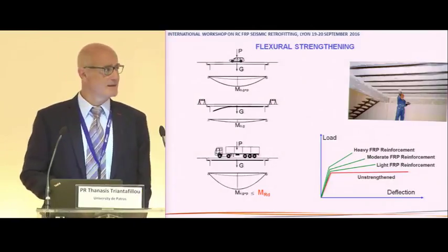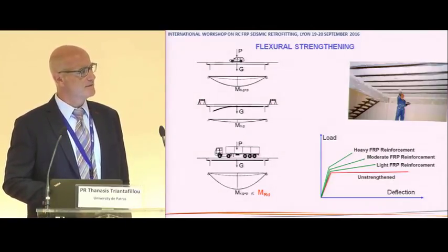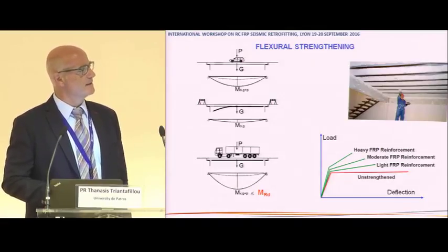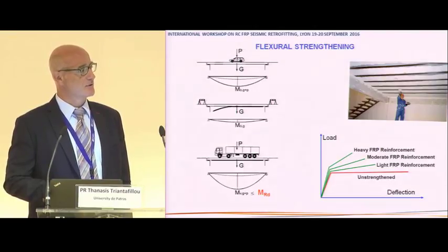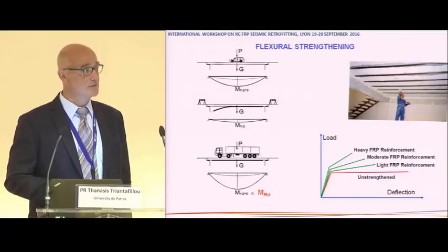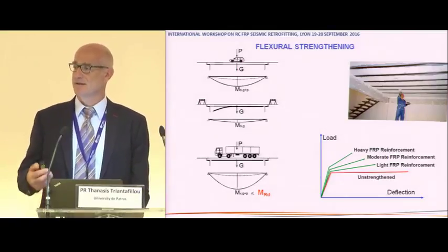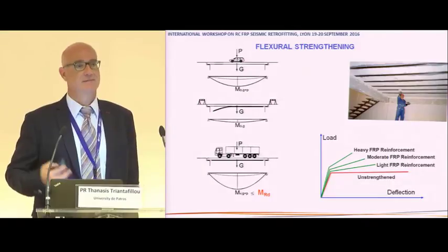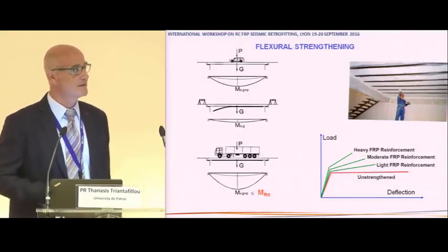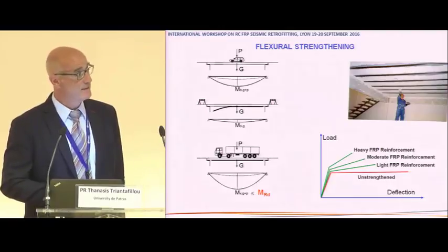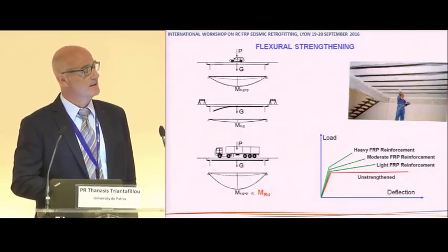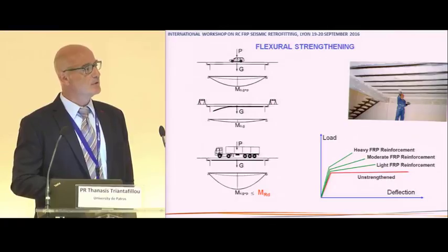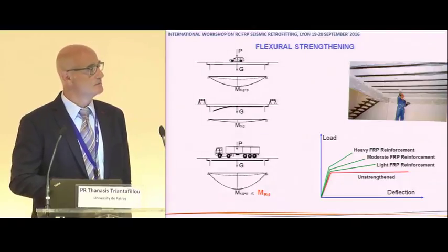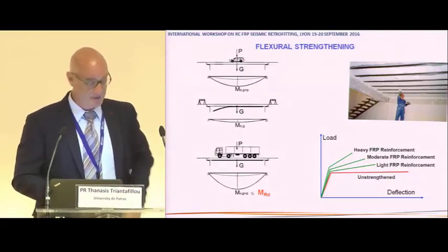The point to remember here is that we don't really change the stiffness. There is a very slight increase in stiffness. Of course, there is a lot of strength gained by the method, but there is also a reduction in ductility. This is not due to the fact that we add FRPs. This is due to the fact that we increase the amount of tension reinforcement. And it has nothing to do with the material itself. And most likely, failure is brittle, is catastrophic due to the sudden debonding of the member, unless we do something to prevent it, unless we use anchorages, for instance.